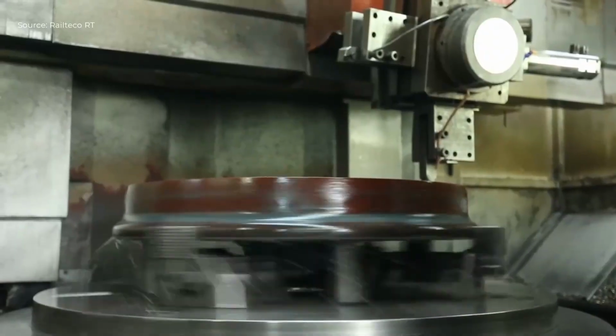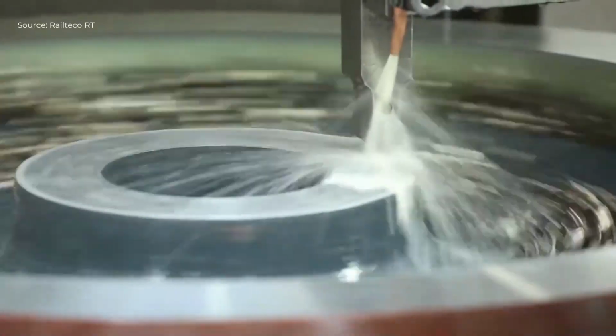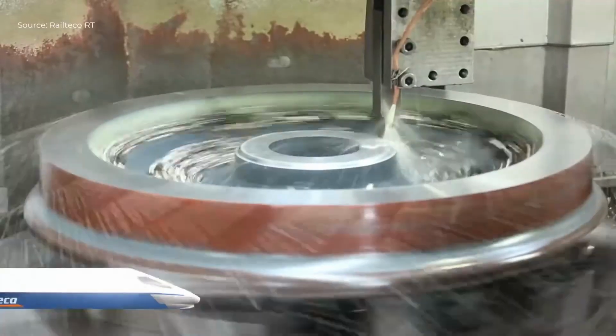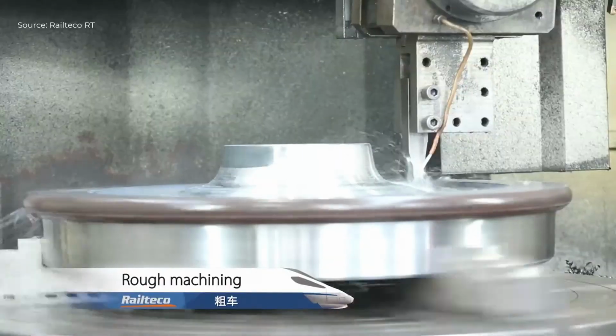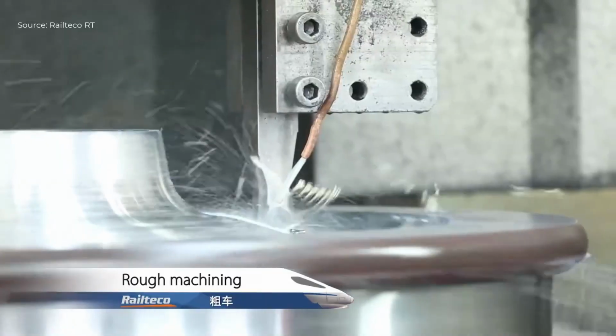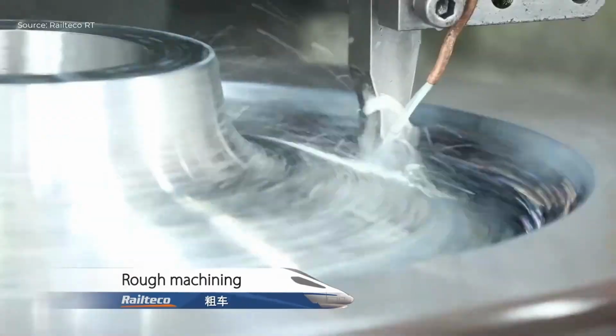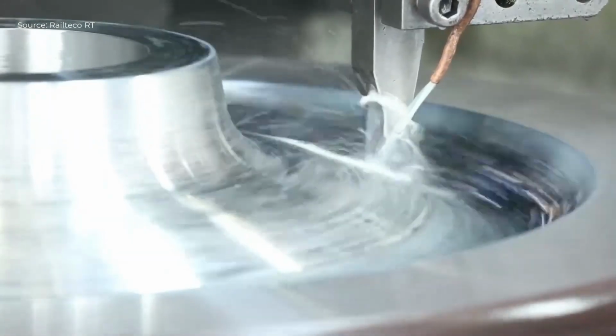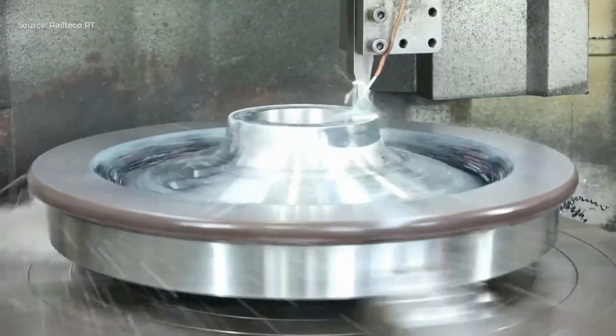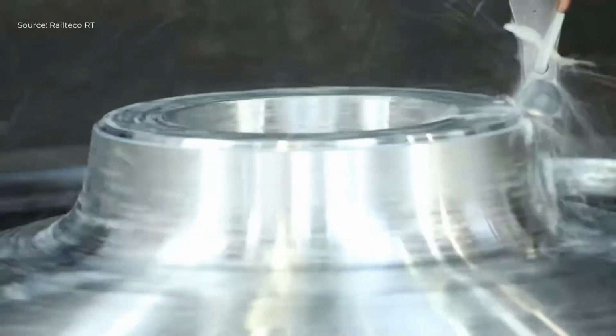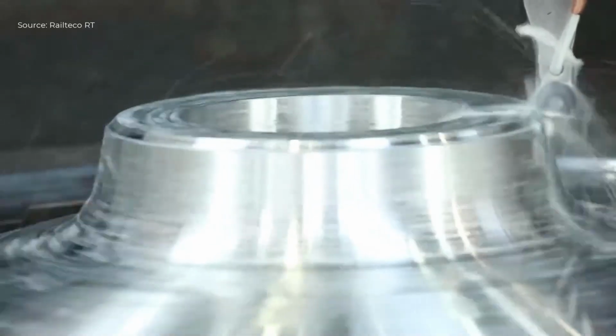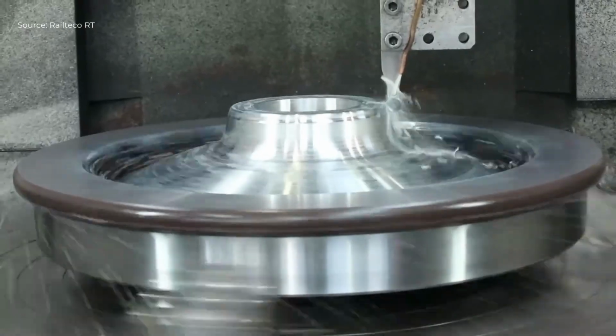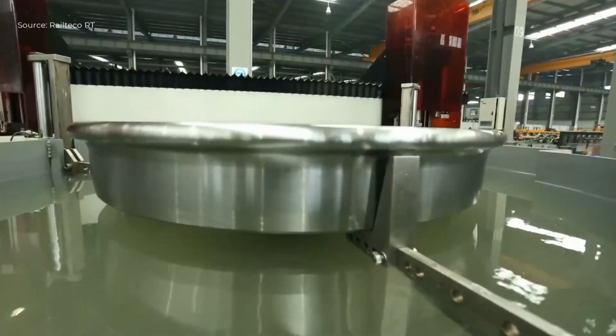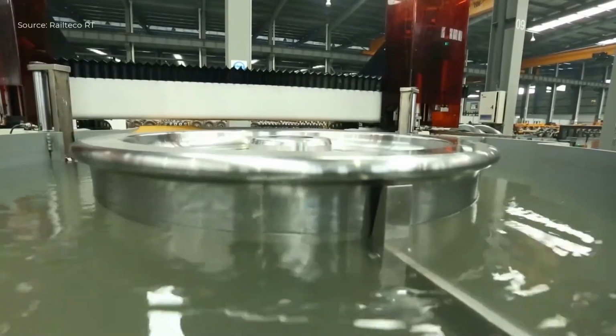The process starts with raw wheel blanks, stored before rough machining on CNC vertical lathes, which remove the forged oxide layer and shape the wheel's profile. Full immersion ultrasonic testing is then conducted to detect internal defects. The wheels proceed to finish machining, where high-precision turning operations refine critical geometries such as tread, flange, and bore, according to design tolerances.